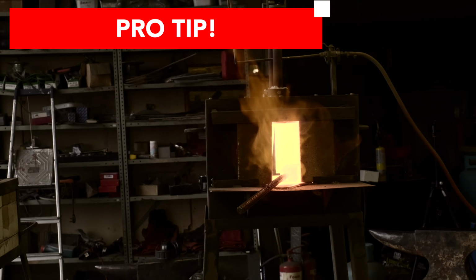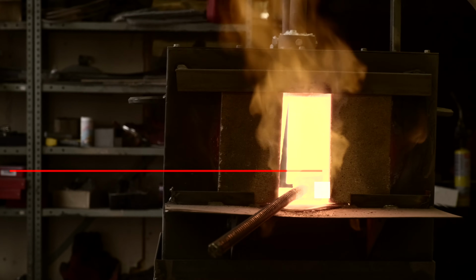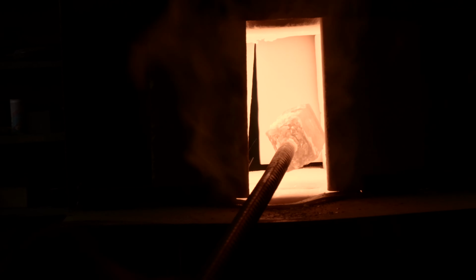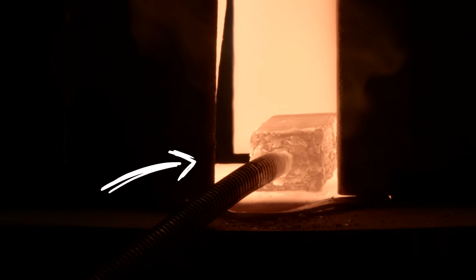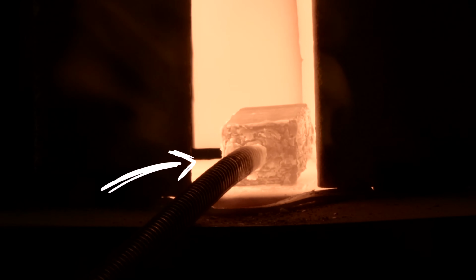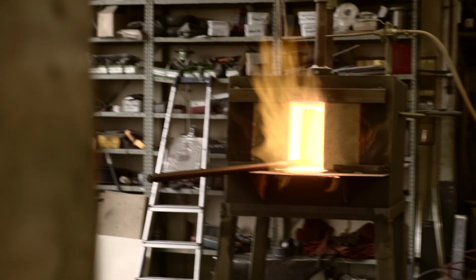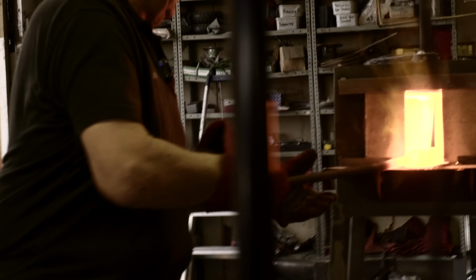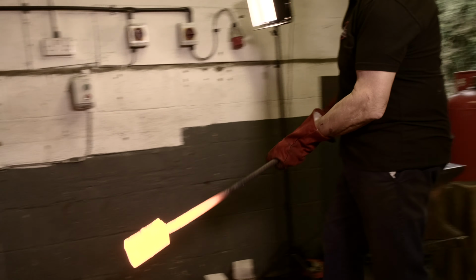Now if you look carefully back into the forge, you can see the metal is a much darker colour. That's because the temperature's lower, it's got cold while it's been in the forge itself. As it gets hot again, the colour of the steel billet will come up so it's looking the same kind of colour as the actual brickwork around it. That tells me it's up to temperature. Okay, so we're just about up to temperature. It's just a case of heat after heat, keep him in the forge.